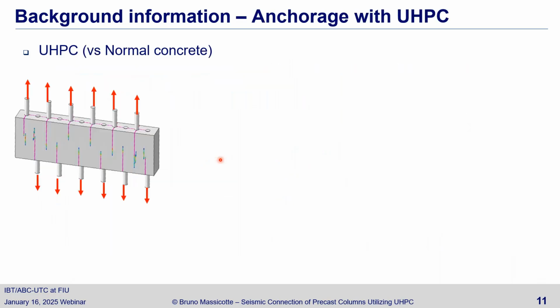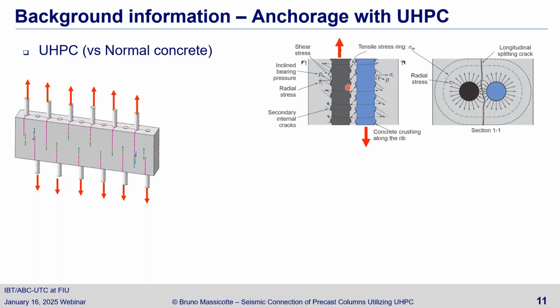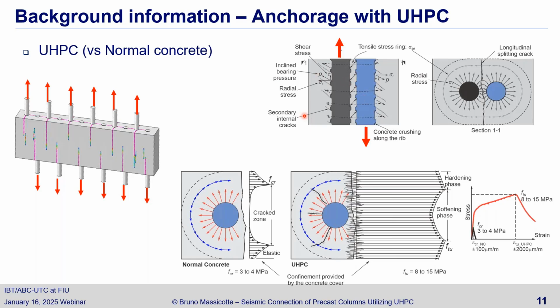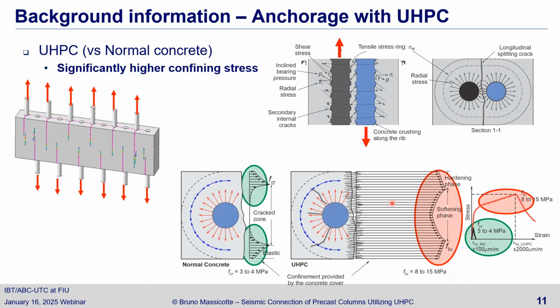If you pull on a series of bars like that in a joint where bars will be lapped, that puts a lot of pressure on the concrete and induces cracking into the material. With UHPC, there's no crushing on the ribs here. It's mostly the tension of the material that governs the behavior. If you look at normal concrete shown here, you get little confining effect, because normal concrete has a very low tensile strength. However, with UHPC, you get very high tensile behavior and ductility, which provides very good anchorage, significantly higher than normal concrete.